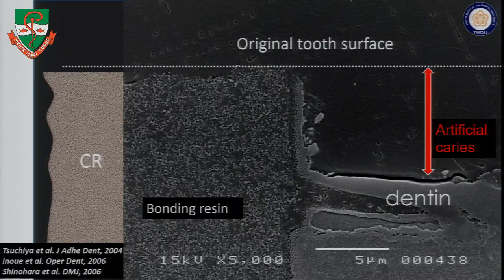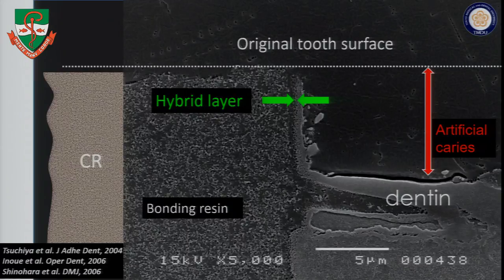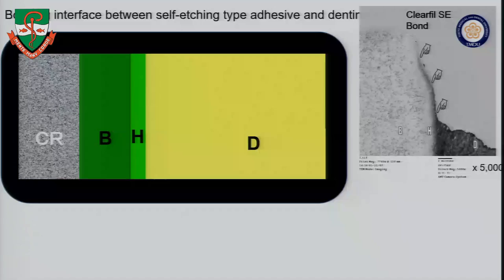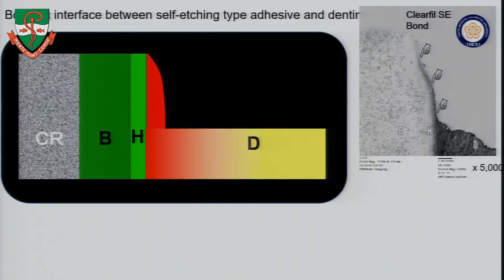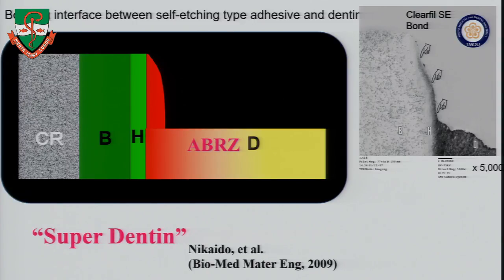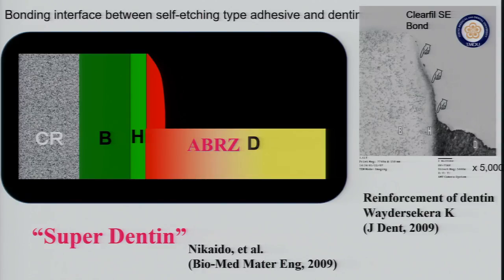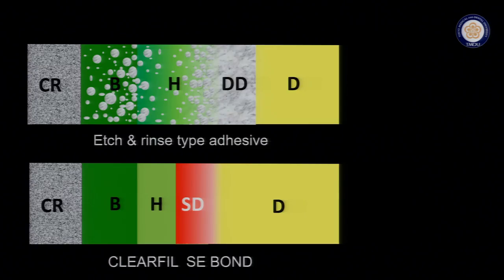And when we observe this part very carefully, of course, we observe the very thin hybrid layer, and adjacent to this hybrid layer, we observe the dentin-like structure still remained even after acid and basic solution attack. That's why we named this layer superdentin. Dr. Nikaido, my colleague, named this layer superdentin, and the term superdentin was already accepted in the international journal. Okay, I hope Dr. Nikaido will give lectures about this kind of interface. So this is the difference of the interface in case of etch and rinse and the two-step self-etching, including the superdentin formation.